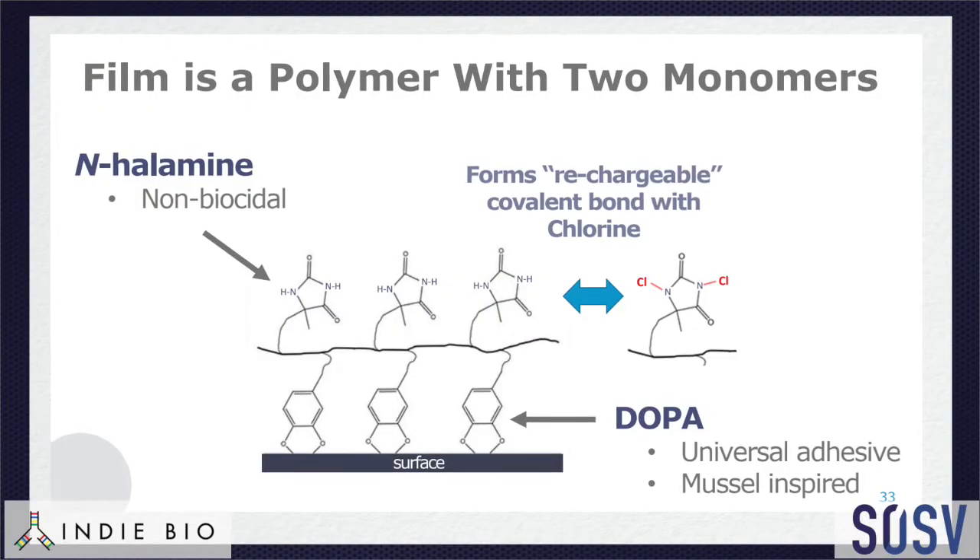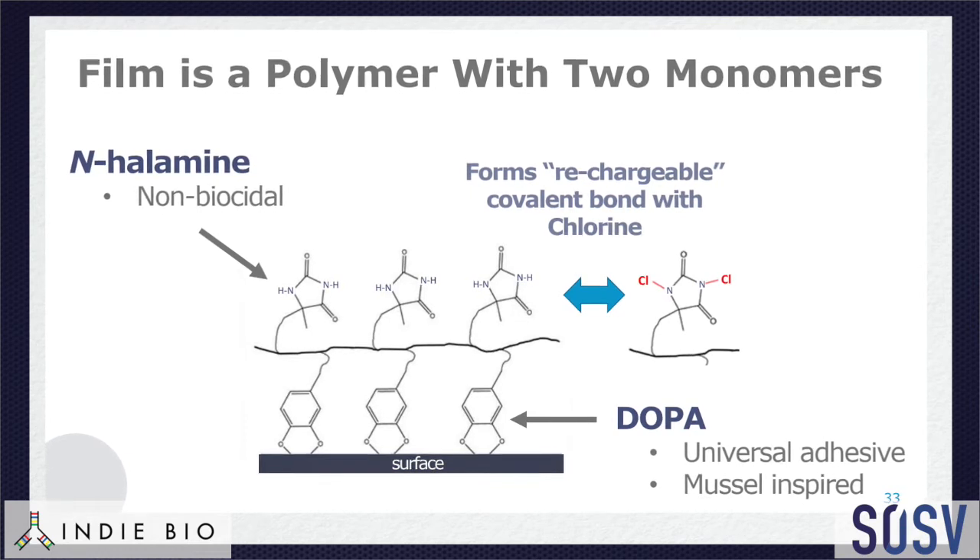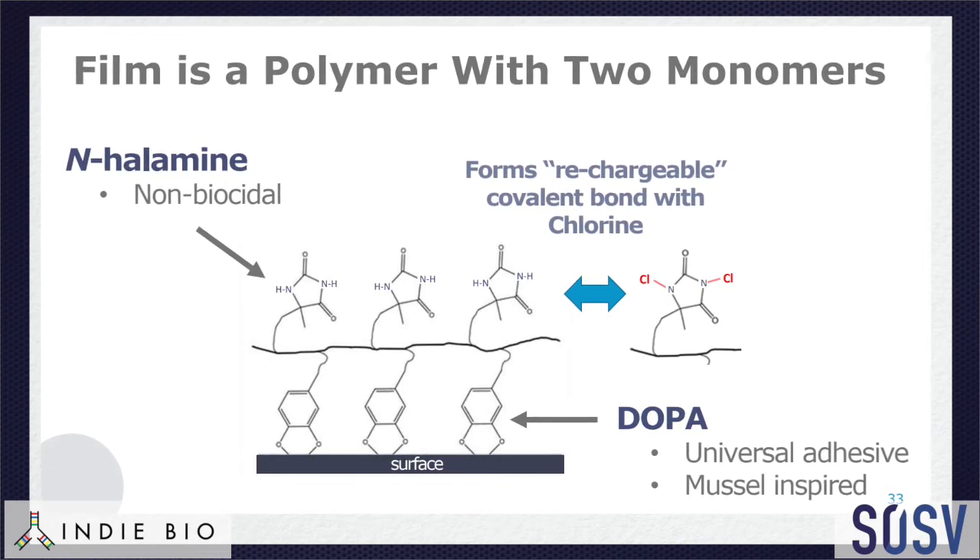So you mentioned that there are two substances in Halofilm. The other one must be something that extends the life of that film — what is that? That's the adhesive part. The adhesive is a bio-inspired adhesive that's derived from mussels. It's what mussels use to stick to almost anything in an aquatic environment — barnacles are usually a better visual, but mussels can really adhere to almost anything in an aqueous environment. The spray itself is mostly alcohol, but a little water. And once the alcohol evaporates, the polymer comes out of solution and starts sticking to the surface. Something intrinsic about the chemistry of those two molecules allows the sticky substance to be layered, and then the N-halamine to be on top of that.